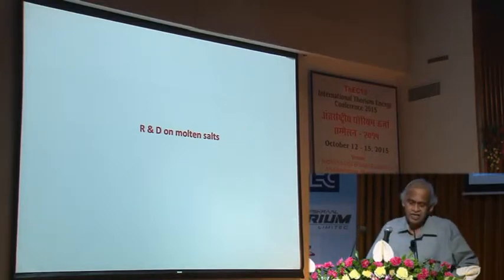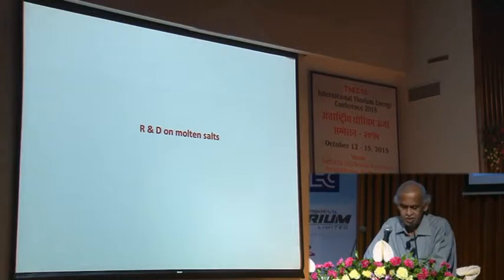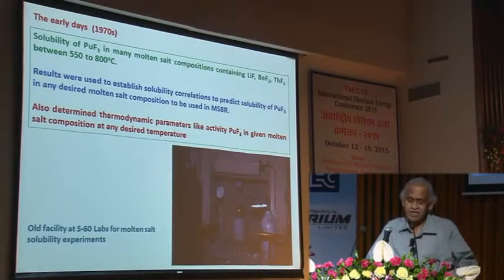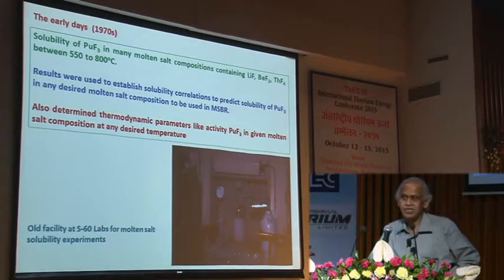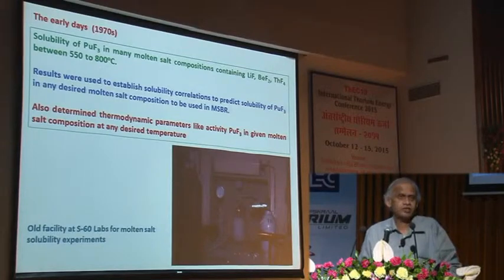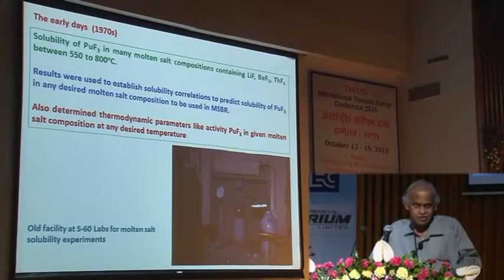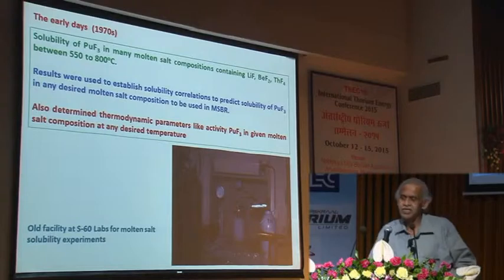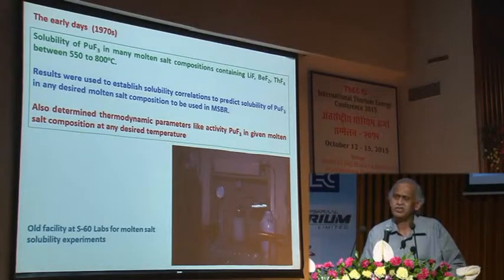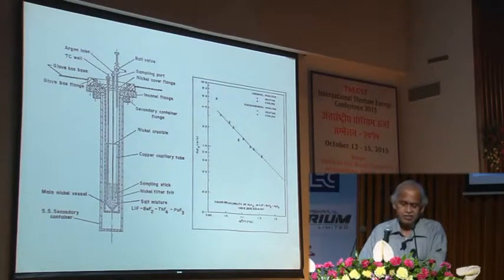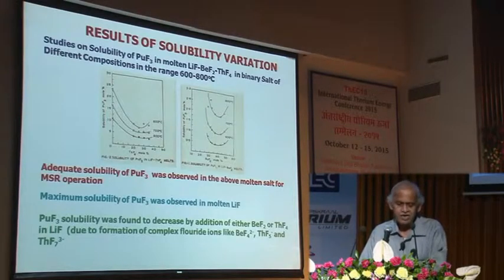to go to the R&D of molten salt systems. Way back in the 1970s, when Oak Ridge was really actively pursuing this, we also wanted to contribute, and in that way in the 1970s we studied the solubility of plutonium fluoride in many salt systems, and then we were able to fabricate some of the apparatus that was required, and then we were able to show the solubility variation of lithium fluoride, beryllium fluoride, thorium tetrafluoride in binary salt mixtures at different compositions.